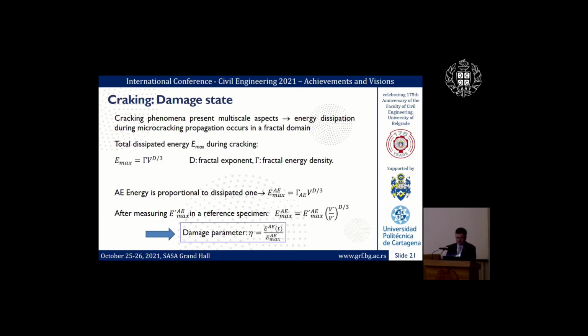An interesting thing about cracking phenomena is that it presents a multi-scale aspect, so it can be studied by using fractals or fractal methodology. It has been found that energy dissipation during microcracking propagation occurs in a fractal domain that is between a surface and a volume. So the total dissipated energy during cracking is given by that relationship, where it is proportional to what is called fractal energy density, a parameter that is independent of the size and only depends on the material, and to the volume of your specimen elevated to the fractal dimension divided by 3.